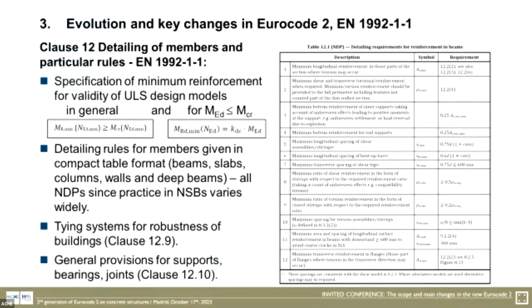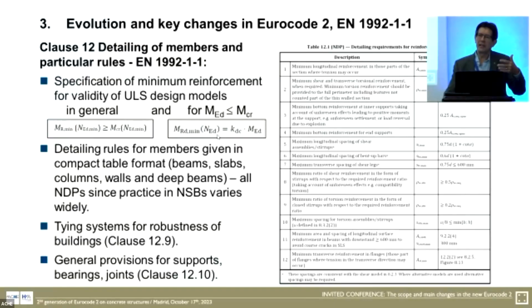However, for members where the action effect does not cause cracking, we give this provision here to the right, where we allow to provide lower amounts of minimum reinforcement, such that the resistance of the section with this lower minimum reinforcement exceeds a factor times the applied action effect. This coefficient K goes from 1.3 for reinforcement ductility class A, so low ductility, down to 1.0 for ductility class C, high ductility.